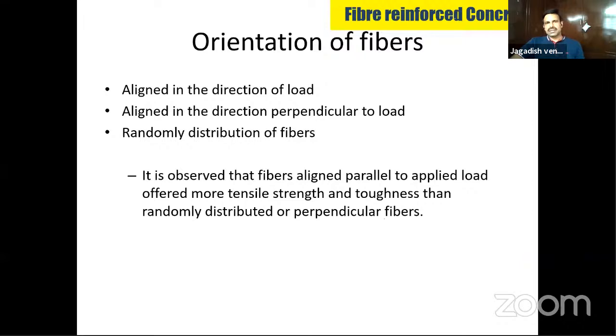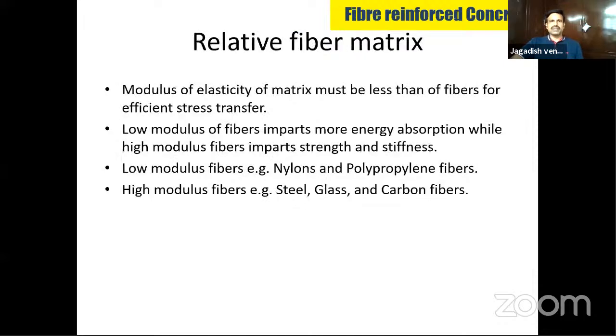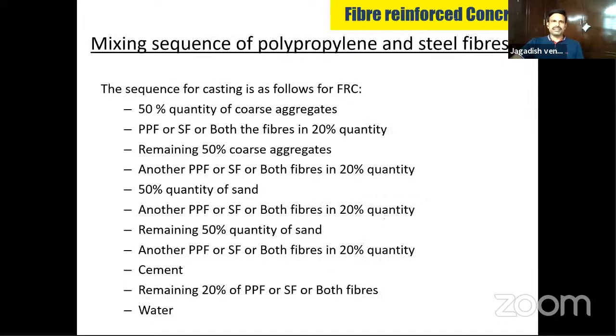Orientation: how do you orient the fibers? In the direction of load, perpendicular to the load, or randomly distributed? In general concrete applications, we usually distribute them randomly. But fibers aligned parallel to the applied load offer more tensile strength. So when you place fibers for special applications, you get more strength and toughness compared with randomly distributed or perpendicular fibers. Low modulus fibers impart more energy absorption compared with high modulus fibers. Low modulus fibers are nylon and polypropylene. High modulus fibers are steel, glass or carbon.